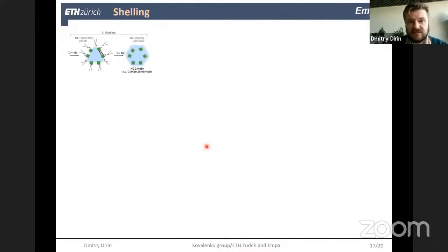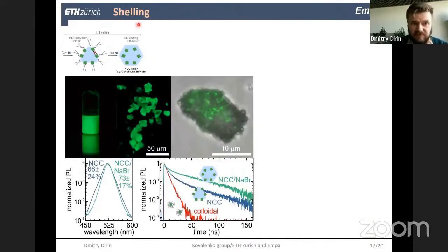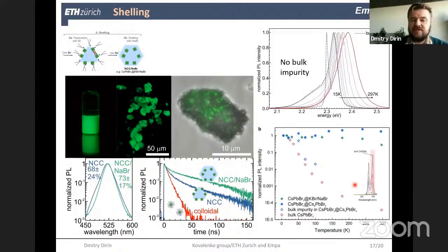Then on the second step, if we attempt this shelling, indeed we don't have merging of nanoparticles, and we still have a very bright material. We don't change the PL peak position in this case, and the photoluminescence quantum yield remains nearly the same. What is important during this shelling step is that we don't have formation of bulk cesium lead bromide, and this we confirm by the absence of bulk emission from cesium lead bromide, which can be observed only at low temperatures.